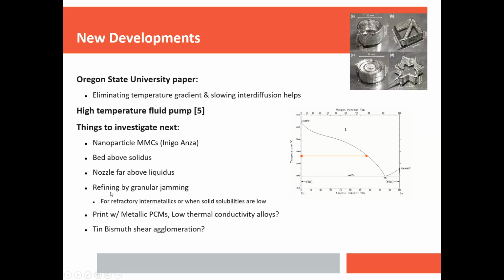another interesting thing to look at is refining metals by granular jamming. So if you look at this tin zinc phase diagram here, if you have some composition in the middle here, you squeeze out the liquid, and the solid fraction you're going to get is essentially pure zinc, since there's almost no solubility of the tin and the zinc. And you can do this if there's refractory intermetallics. I believe it's called rheo refining in the literature. But if granular jamming is a robust process in these systems, then rheo refining may be a very simple way to get reasonable purity of metals when processing recycled metals, perhaps. You can, for example, pull out titanium and nickel impurities in aluminum this way, because the intermetallic compounds are so refractory.